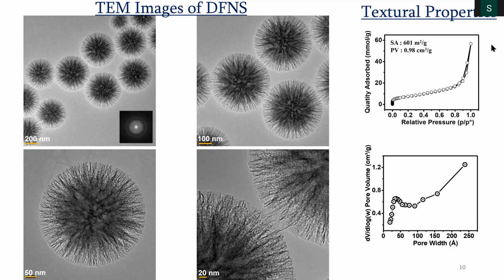There's a question by Dr. Ashok Behera. Are they porous? Yes, that's what I'm saying. They are a porous material. That's why, otherwise you cannot have such a high surface area, right? So these are all porous material. But definition of porosity here is different. Generally, pores are closed, tubular or random pores where you have one entry and one outlet. Here, these are the fibers open from all the sides. So they are porous, but then those pores are accessible from all the sides, which has its own advantage and disadvantage.